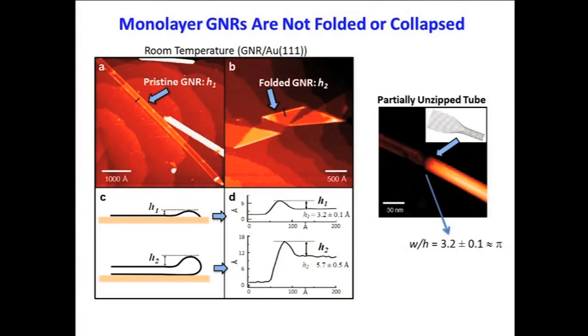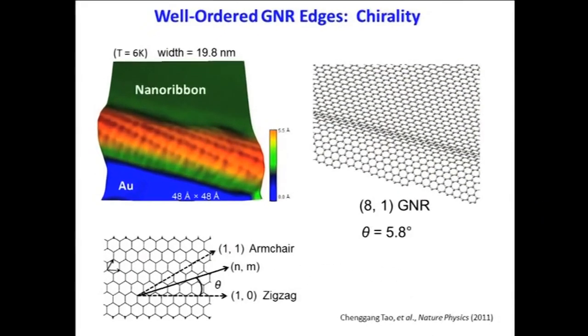And so now that we know that we have these nice terminal edges of our graphene nanoribbons, we can look at them with higher resolution at low temperature, and investigate their atomic structure and their electronic structure simultaneously. And that's what we did. So here I show a high resolution STM image taken at low temperature of the edge of a nanoribbon that has a width of 20 nanometers, and I'm just zooming in on the edge. So this is the edge, this is gold, and this is the nanoribbon, this greenish stuff, and this orange means that it's taller here. And this is the edge.